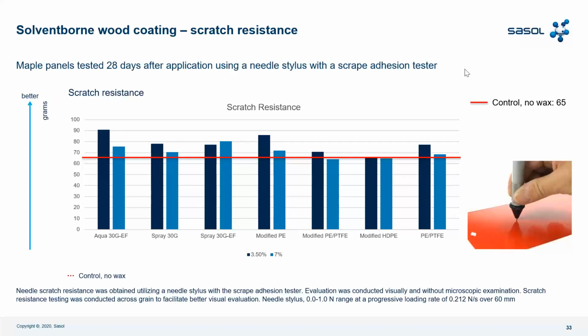You need to read these results with the highest value being the best for scratch resistance. So we have Aqua 30G-EF that achieves a great result with respect to the other waxes and the control. The control was 65 and we achieve around 90 with 3.5%. So better than all the Sasol wax products in this test and also against the competition.